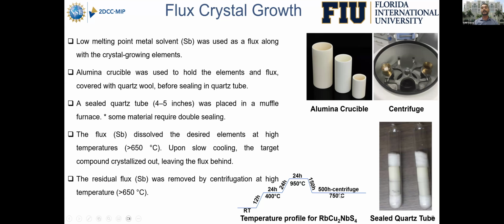And at this particular temperature, we need to centrifuge our material, our quartz tubes, because we need to remove the residual flux, which is antimony, out of our target material. So here we use flux as a main material to grow the bulk crystals.